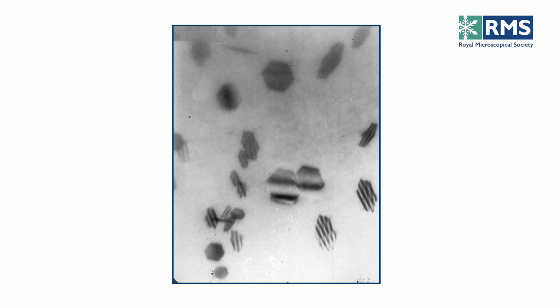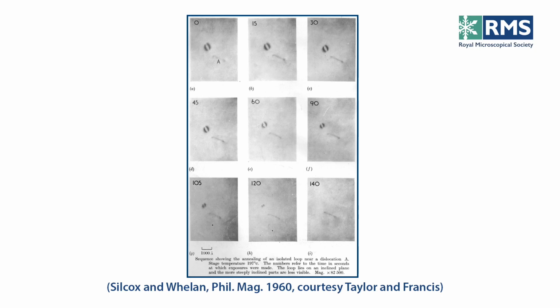I think these are beautiful images. Indeed, yes, they are. They also show the crystallography and the symmetry. And you can see the fringes of the inclined stacking faults that you predicted. Absolutely. Mike Whelan with John Silcox did an experiment in which they made the specimen holder into a heating stage, and that effectively annealed the materials. What happened was that the loops gradually shrank, and they do this by emitting vacancies, and the vacancies disappear at the surface, and eventually the loops disappear.